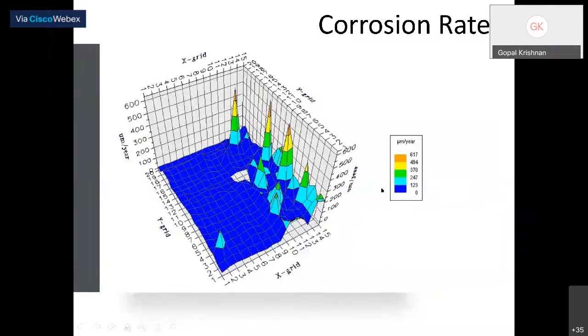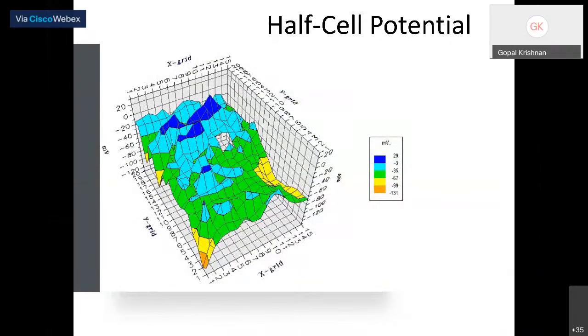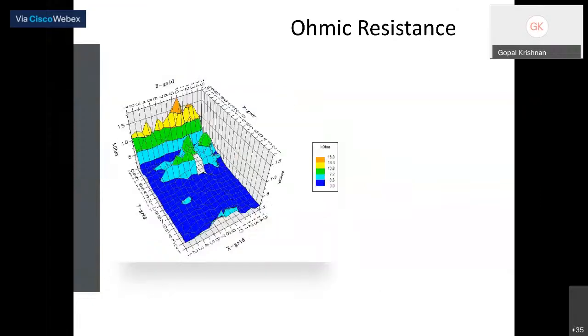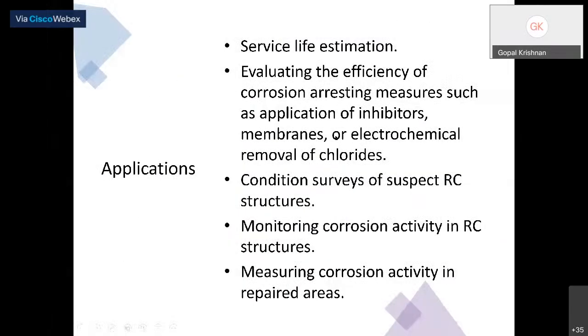The yellow and orange is very much higher, on the severe part. Similarly, the half-cell potential reading, then resistance in ohms. We can use it for understanding the service life estimation of the structures, and evaluating measures such as application of corrosion inhibitors, membranes to protect the structure, or electrochemical removal of chlorides. There is also a latest technique we are using, and also as a condition survey of corrosion activity continuously. This can be fixed permanently.